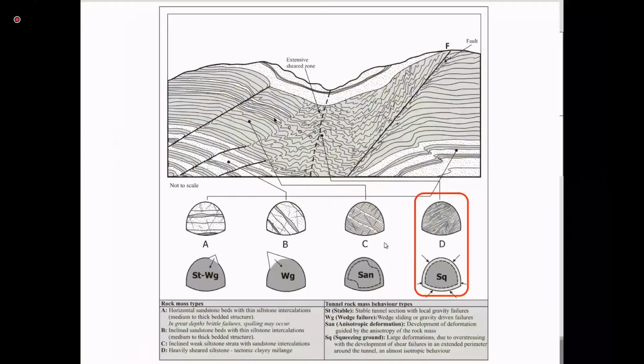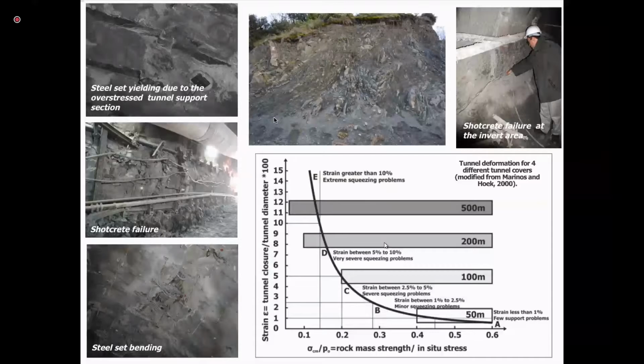And of course, when we have severe squeezing ground and a chaotic structure, then we may have overall squeezing conditions around the tunnel, not anisotropic deformation, but large deformation due to overstressing with the development of shear failures in an extended perimeter around the tunnel. So you can see for type D here the photo of the material and what kind of problems face our tunnels: yielding and shotcrete failures. And you can see what kind of overburden we may experience: few support problems, strain less than 1%, or severe squeezing or very severe squeezing. You can see the different depths where we can face that, just by first approach along our tunnel.